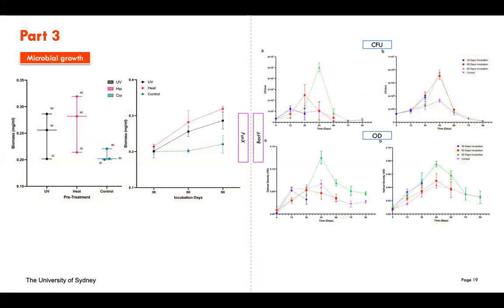So, of course, we did the same thing as we have done on Aspergillus and Engeodontium before. We run on the microbial growth. We want to see how much they are produced after 30, 60, and 90 days. For the fungal isolate, we call this one FunX for now, the growth increases after 30, 60, and 90 days. We can see that the UV and heat-treated samples grow more rapidly compared to the control, which is the one without any polymer being used as a substrate.